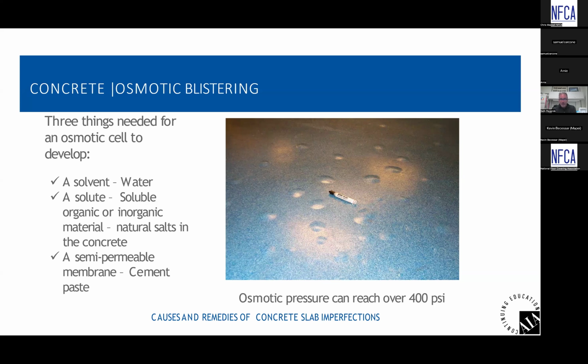create a blister in a resinous material like epoxy terrazzo or a high build epoxy coating. I mean, these are products that have compressive strengths of 10 and 20,000 PSI, and the force of this osmotic blister can blister a very rigid epoxy material, as seen in the picture here. And you take a drill and drill down through this resinous coating, and you have liquid that pops out of that blister, and it's very alkaline, super high, probably pH of 14 on the pH scale.